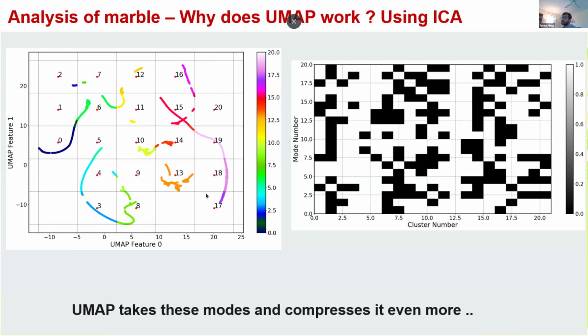So if we take the UMAP features and discretize it in space, so we break it into different components, then we can look at what's actually happening for cluster number 0. If you look in the figure on the right, that's representing one aspect, one phase space in UMAP space, and that's actually taking a bunch of modes together and using them to distinguish cluster 0 versus cluster 1. So conceptually, what UMAP seems to be doing is taking these modes, which are representing different frequency structures, and hence representing different types of damage and moduluses in the sample, and finding that even those are correlated with each other, and I can reduce that down to a few dimensions.